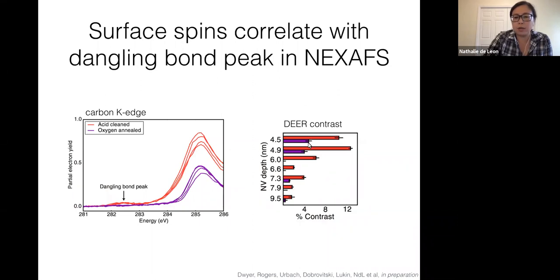So to show that a little bit in a more controlled way, what we can do is look at individual NV centers before and after we do this oxygen annealing, and we can look at this DEER signal for the same NV centers. And we see that the DEER signal gets suppressed by a factor of several, and almost an order of magnitude for some of these NVs. Okay, so we think we have something that we can see in X-ray spectroscopy that correlates with the surface spin signal. But I already showed you a giant pile of data showing that quite a few things change when you do this oxygen annealing. So it's not actually obvious that these dangling bonds really do correspond to these spins that we can see in DEER.